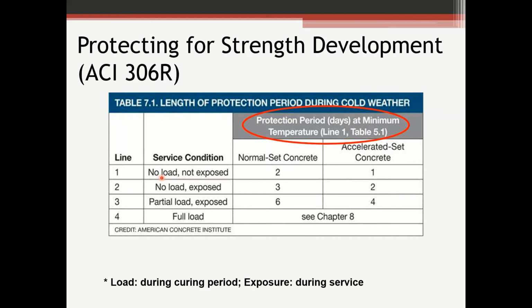So this first line here, no load, not exposed, that could be maybe a footing that's down below the frost line. That's really not going to see much of a load during the first 28 days. And then in its service condition, it's hopefully down below the frost line. So for normal concrete, the protection period is 2 days. If you've got accelerated set concrete, maybe you've got an accelerator in the mix, or maybe you've got type 3 concrete, that protection period is only 1 day. No load exposed, we go up to 3 days. Partial load exposed, we're going up to 6 days.